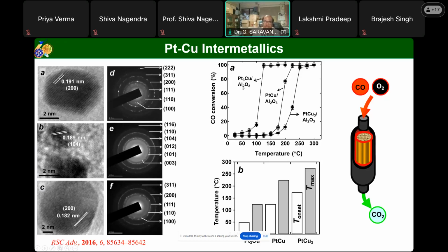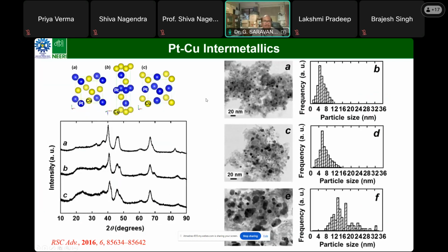So that means when you keep a certain element in the lattice of platinum, you can influence the electronic structure, which can give better performance than the commercial platinum, as well as the same intermetallic structures. So here are the different crystal structures of these Pt-Cu combinations. When you achieve this kind of platinum and Cu intermetallic structure, it shows much better activity than these other two.